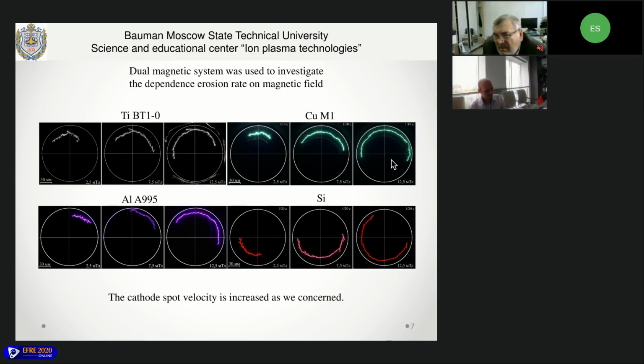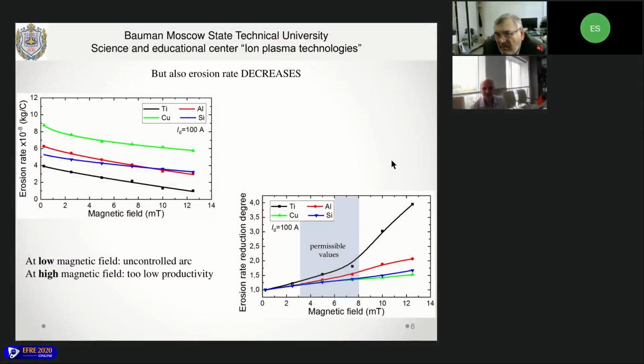Next, the erosion rate was measured by direct weighing of the cathode before and after the experiment. This work was done for different materials, as I said, and with different magnetic fields. So as you can see, the erosion rate is not constant for all of the materials we considered, and also, I think, for all of the materials which can be used for this technology. The erosion rate decreased with increasing magnetic field. You can see this for titanium, for copper, and for other materials.